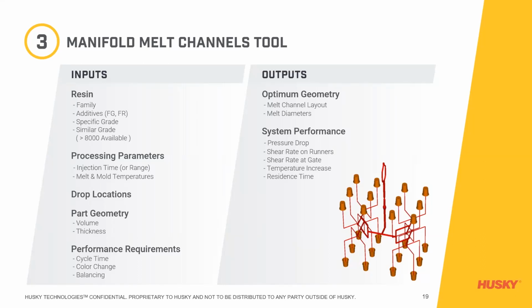Are we looking for specific balance requirements? So those are all the inputs, and the output to that is a melt channel layout and melt channel diameter, which optimizes the geometry of the manifold. System performance gives us the predicted pressure drop, the shear rate within the melt channels, the shear rate at the gate, and the temperature increase as a result of that shear rate.